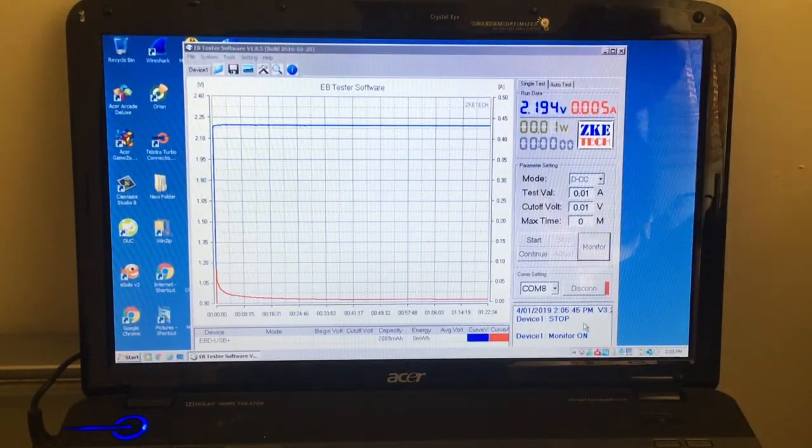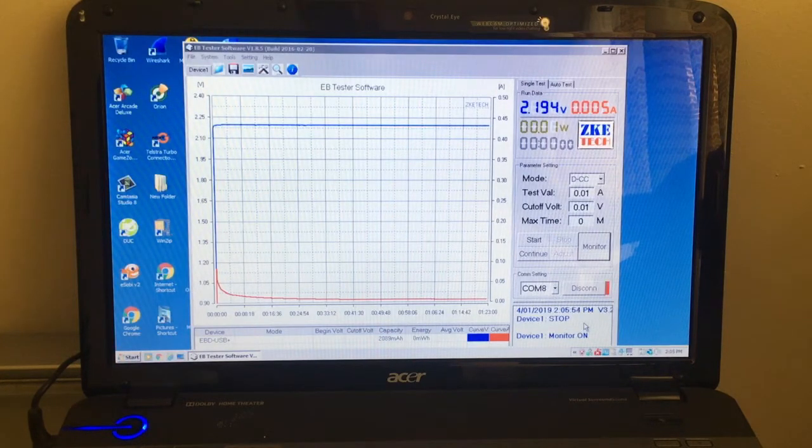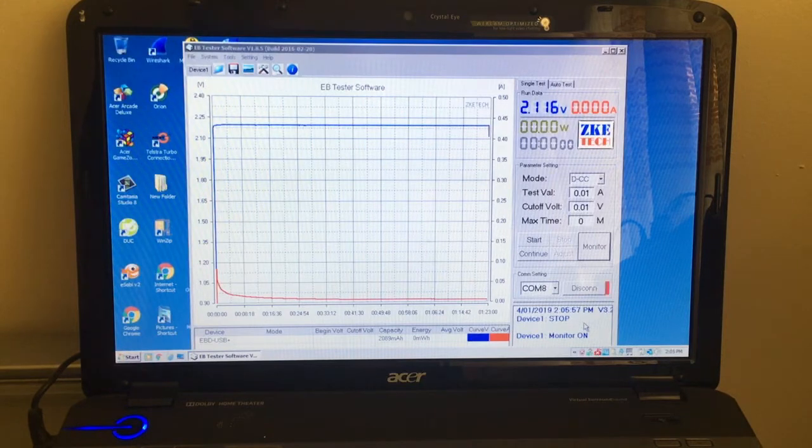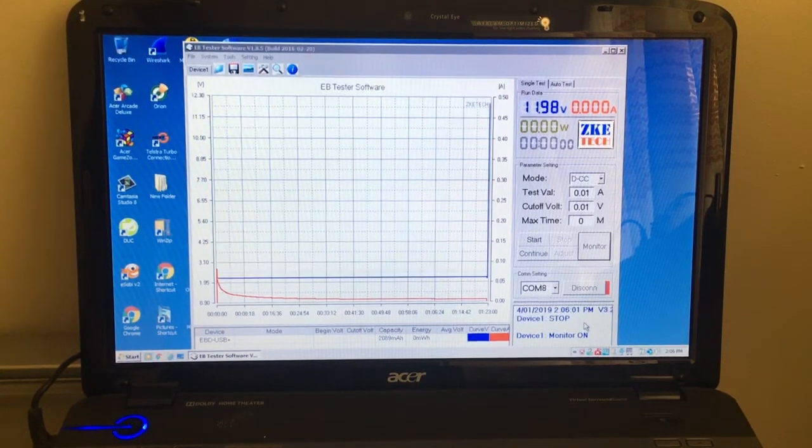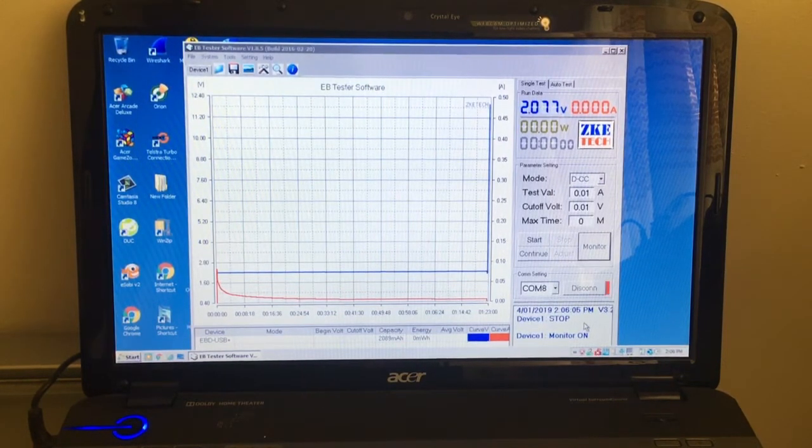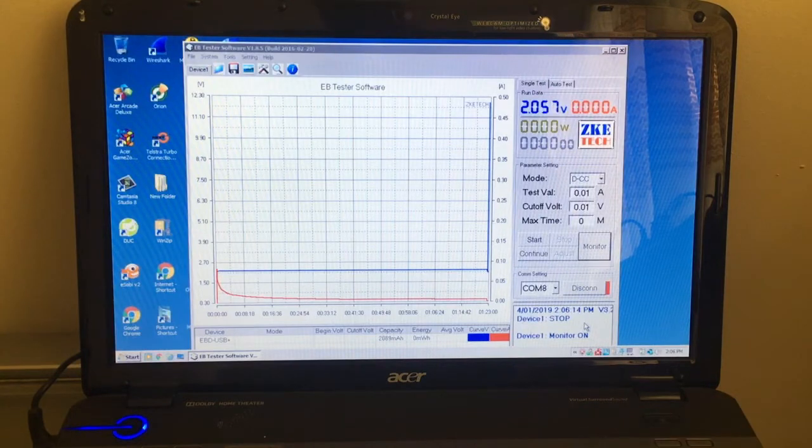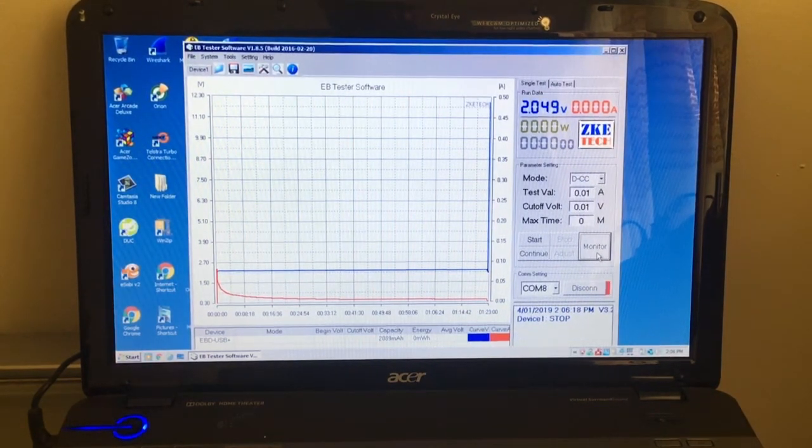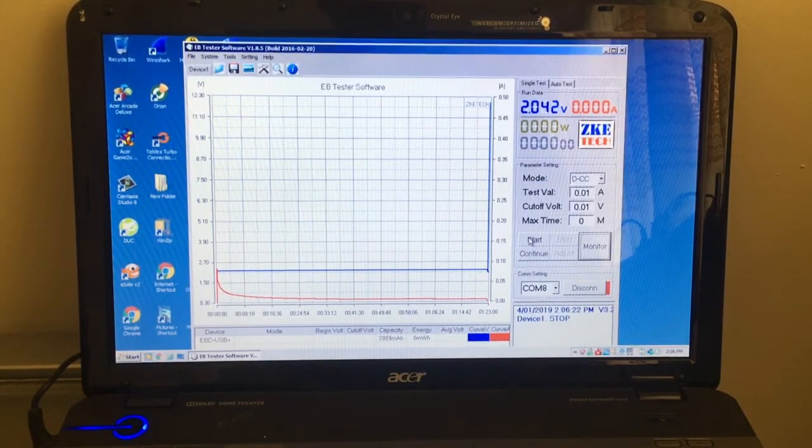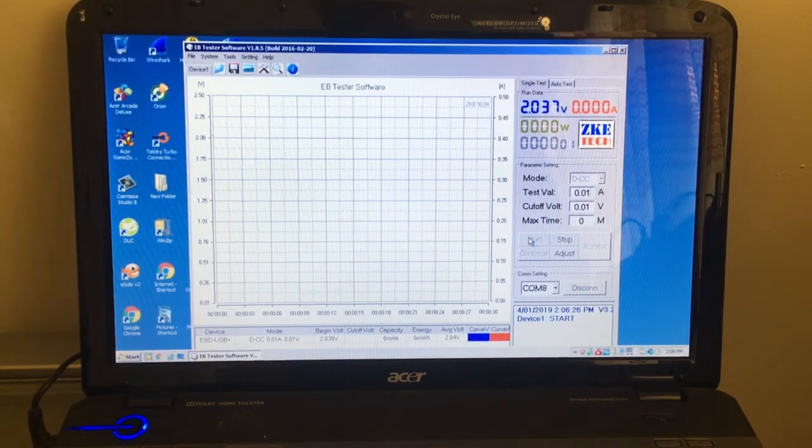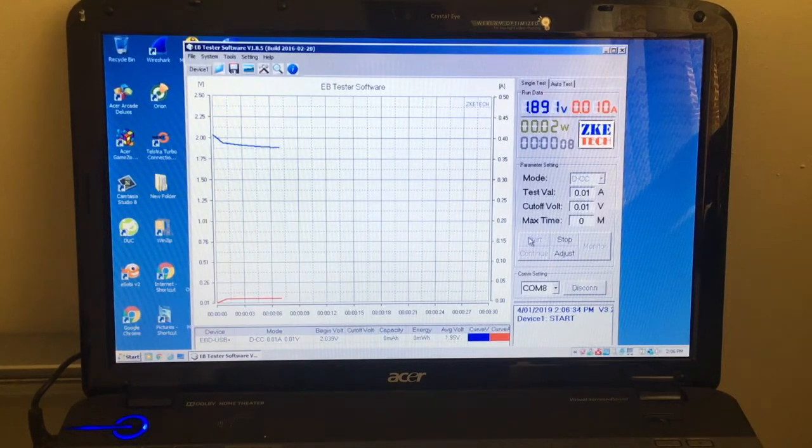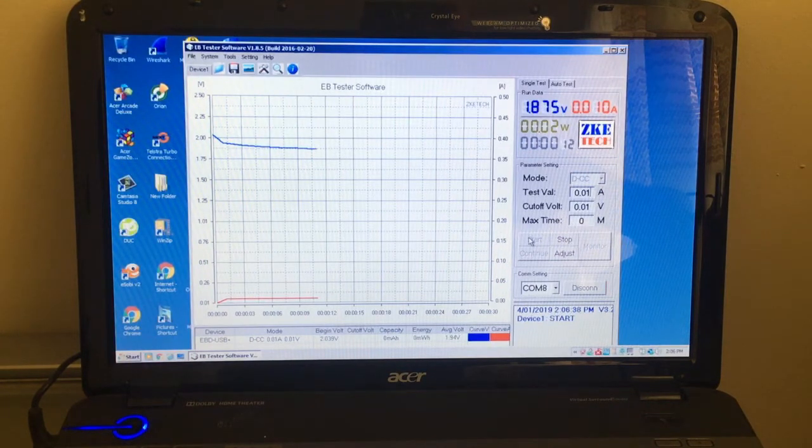The cell seems to be stable in its charge this time. It's been sitting at 5 milliamps for the last 22 minutes. So I don't think it's going to increase anymore. So it must be at max capacity or something. So I'll disconnect the charge. And connect the data logger to the cell itself. We should have a voltage now. We're at 2 volts holding sort of. Stop the monitoring. And we'll do another discharge. Second discharge for this cell. Hopefully it's improved. I think it was 9 milliamp hours last run for an hour. Voltage is sort of dropping fairly quick.